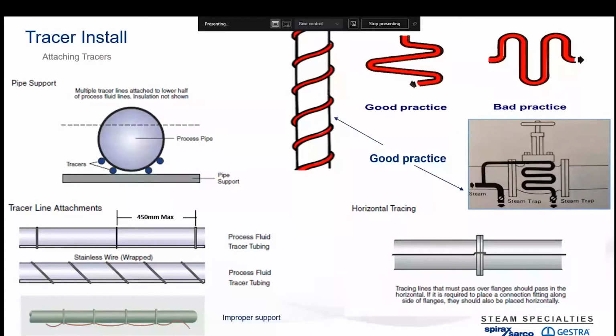In terms of tracer install, there are certain guidelines around that. Certainly, the tracer itself should be installed at the bottom of the pipe, ideally, where we're looking at multiple tracer install, at 30 to 45 degrees. Really, we should not be tracing at the top of the pipe, because the chances are that there's likely to be air there and we don't want to be heating up air. In terms of attachment, we want to get that tracer tube as close to that product line as physically possible, and then we put bands in around 450 millimeters max. Stainless steel wire can be used, but what actually happens is that the wire can snap over time, and then we get a situation where we get the pipe sagging and creating low points.